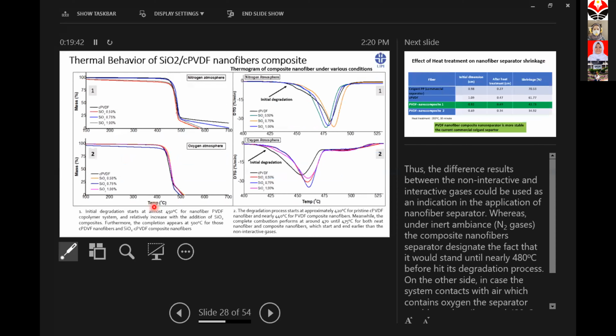This is an important point when we develop the separator. We measure the thermal behavior using TGA. You can see the effect of silica on the degradation of the polymer composite. In pristine PVDF, degradation starts from 420, but in the composite, the initial degradation is around 440 centigrade. It means we can control the thermal property by adding the nanoparticle.